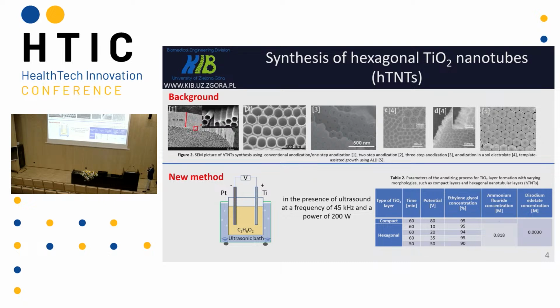So we decided to make the anodization process faster. So we added ultrasound to our method, but it doesn't allow us to obtain this structure. So we were focused on the spaces between single nanotubes, and our hypothesis was that when we make this space so close, it will allow us to obtain the hexagonal titanium nanotubes.